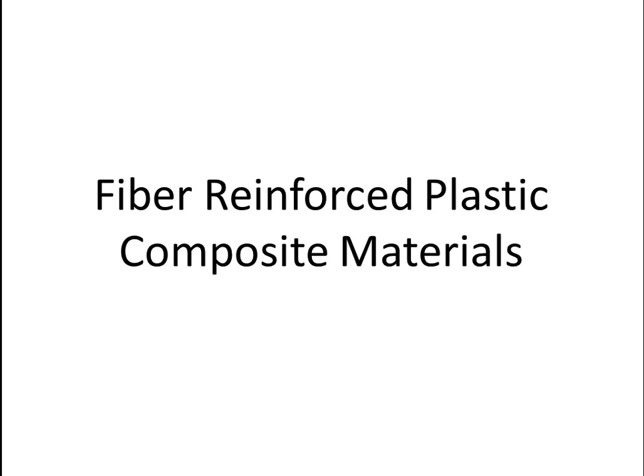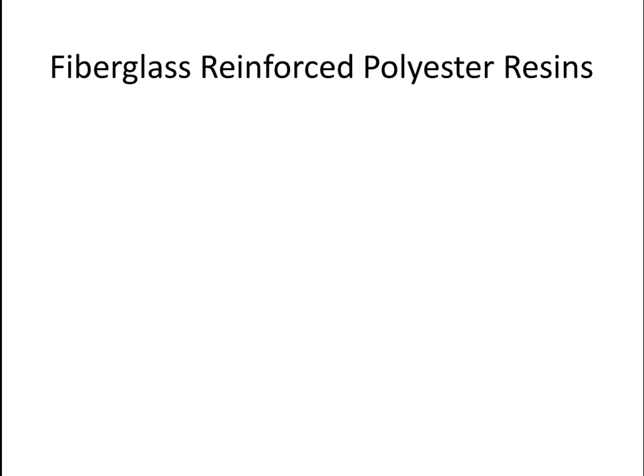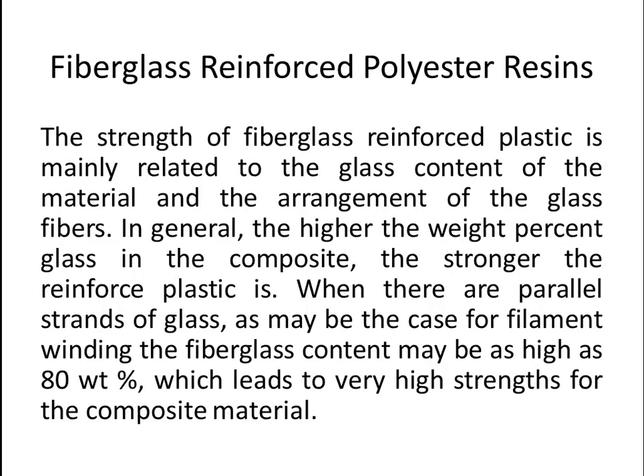Now let's talk about fiber reinforced plastic composite materials — specifically fiberglass reinforced plastic resins. The strength of fiberglass reinforced plastic is mainly related to the glass content of the material and the arrangement of the glass fibers. In general, the higher the weight percent glass in the composite, the stronger the reinforced plastic is. When there is parallel alignment of glass fibers, as may be the case for filament winding, the fiberglass content may be as high as 80 percent by weight, which leads to very high strength for the composite material.